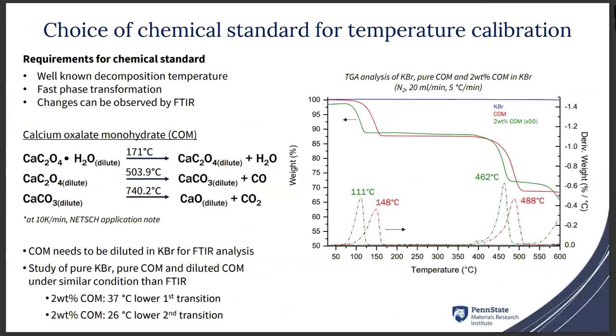And we can see in the theoretical value, those values are taken from an application note from NETZSCH. They use 10 Kelvin per minute, I use 5, and already for the pure sample, I have quite a difference for the first transition and the second transition.